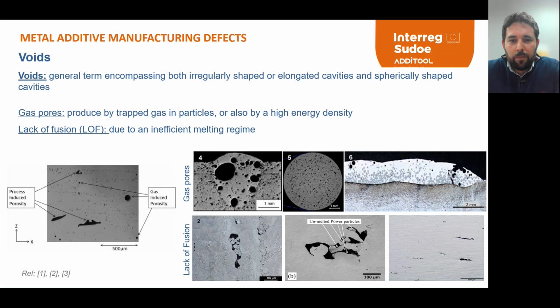So voids is a general term for both irregular and spherical shaped cavities. So when we talk about voids, we are including gas pores and lack of fusion. So gas pores, you can see some images in here, on the top, could be produced by trapped gas in particles, for instance, gas in the powder itself, but also could be produced by high energy, so that gives you spherical cavities.